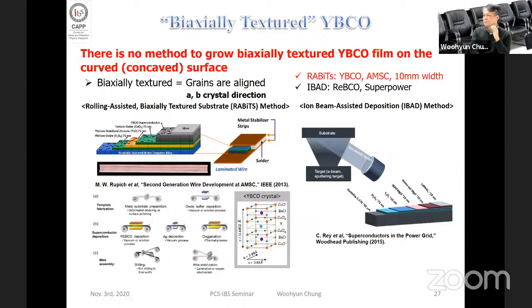naturally, but it has a big problem, which is YBCO has texture. It's biaxially textured. So if you have a different angle, it doesn't work as well as the 90-degree angle. So the grain has to be aligned with our magnets. So in a three-dimensional microwave cavity, it doesn't work. Sputtering YBCO into a concave microwave cavity doesn't work, and nobody wants to do that.